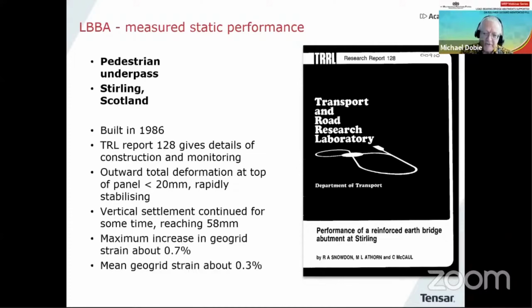And when it came to the geogrid itself, the maximum increase in strain during the service period was about 0.7%, with a mean value of about 0.3. And I've got a feeling that this data was part of the contribution to those early limits that are still published today in BS 8006 about a mean strain limit of 0.5% for load-bearing bridge abutments.